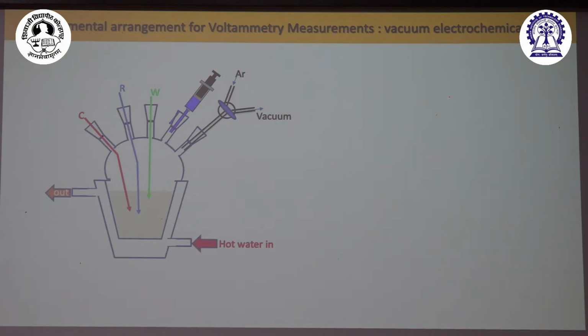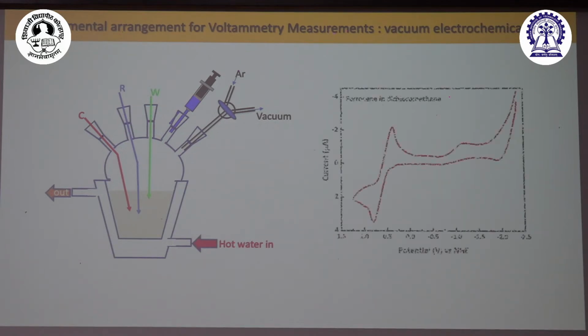One more problem: we can't use Ag/AgCl or calomel as a reference electrode in a non-aqueous solvent. Why? Because those electrodes are aqueous based. We don't want even traces of moisture, and I can't put a whole aqueous electrode in the non-aqueous solvent. So normally we use a quasi reference. We use a silver wire as a reference and do all the measurements. It's not a real reference, it is a quasi reference. Then, once we finish all the experiments, we add ferrocene and standardize. I can now calibrate all the potentials with the redox potential of ferrocene. That's why our potential is very accurate.